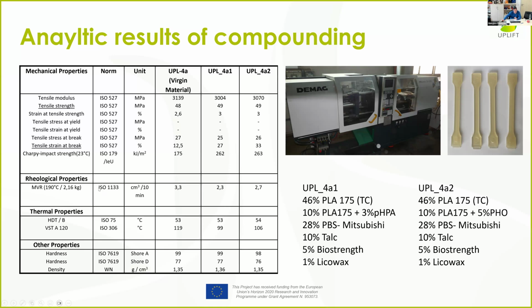The second most important part is the rheological properties, because the MVR, the melt volume rate, shows us if it's processable or not. And for the extrusion type, we need smaller values. And we see the incorporation of both components decreased the MVR value, which is very, very good.